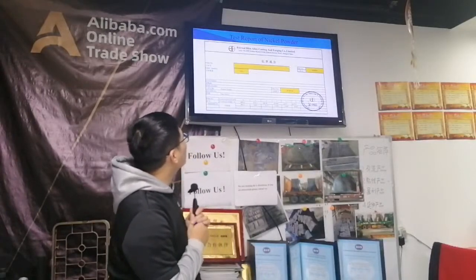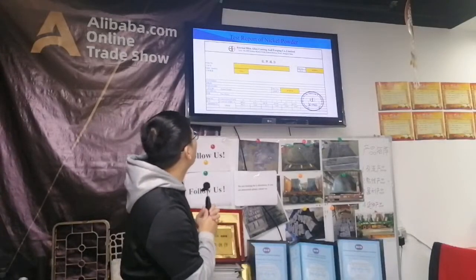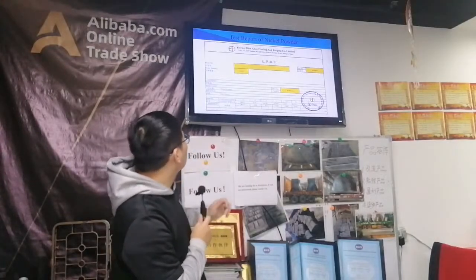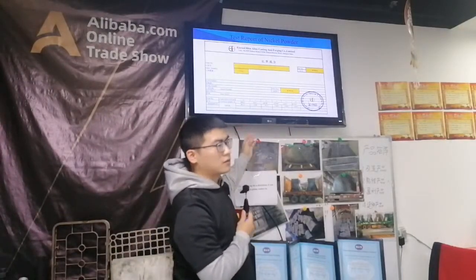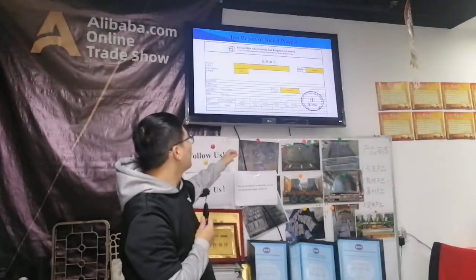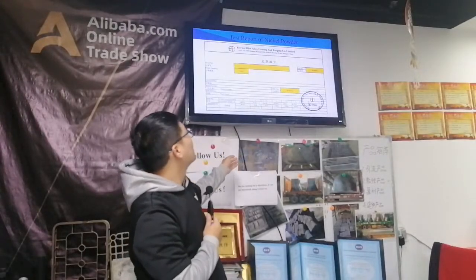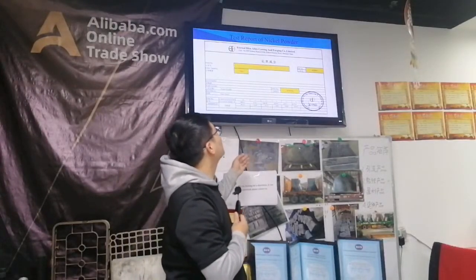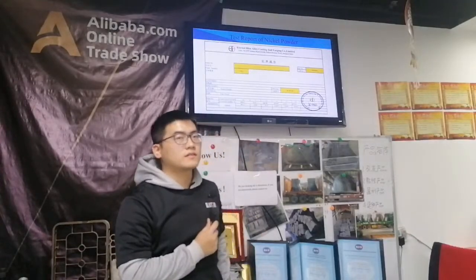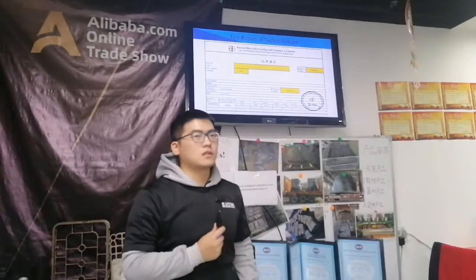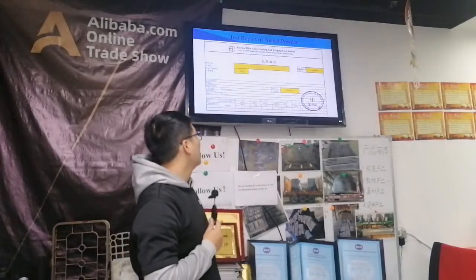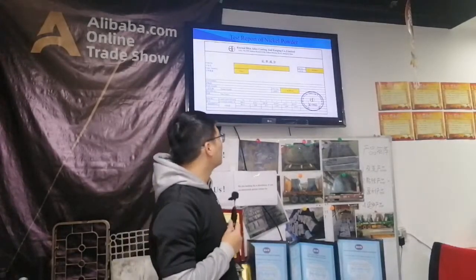As you see on the screen, the nickel powders after test, the standard purity is about 99.77%. This is the test report of the nickel powders, so our nickel powders are pure enough to meet your requirements.